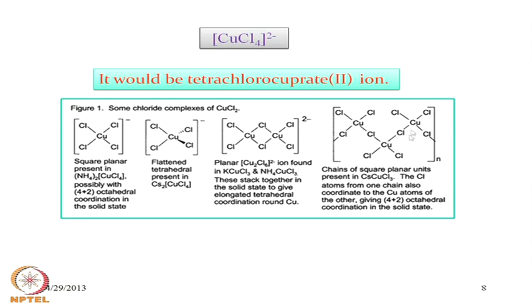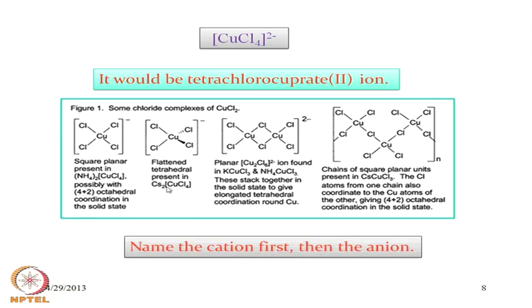Similarly, if the bridging is extended further, it is another form of CsCuCl3, which is completely different from Cs2CuCl4. This particular chloride is in the chain form, so the chain continues in a zigzag fashion, and one chain also coordinates to the copper atoms of the other, giving this also a 4 plus 2 octahedral coordination in the solid state. So, in the solid state, one chain of one particular plane is sharing the chlorides from the other chain, giving a typical octahedral. So, the copper metal center will always have some tendency to attract another ligand which is already bound to the adjacent copper center. So, here also while we have the corresponding cations present, the name of the cation comes first, then the anion.